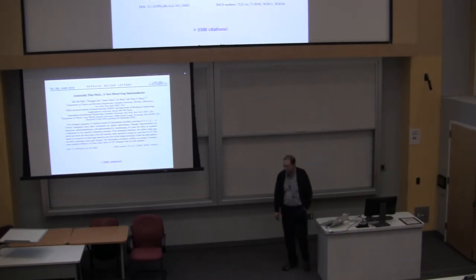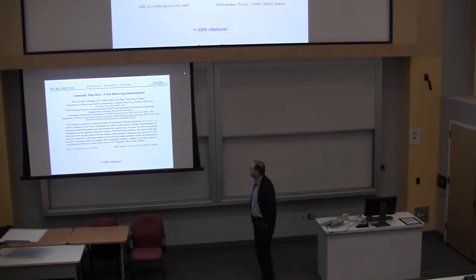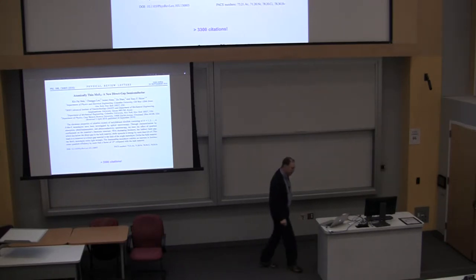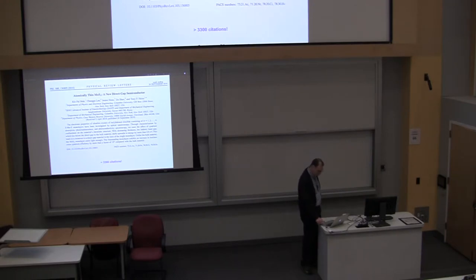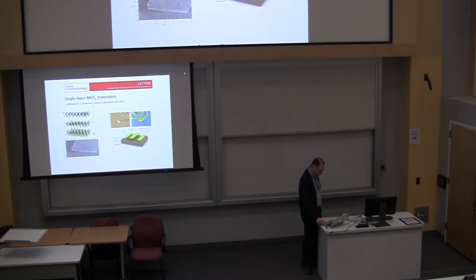So what really broke open the field was this paper where they discovered that if you take moly disulfide and you make it thin enough, it goes from being an indirect band gap semiconductor to a direct band gap semiconductor. This paper had 3,300 citations last year, probably up to 4,300 or something by now. So this really was quite a discovery, and it made people start thinking about these materials as functional materials.